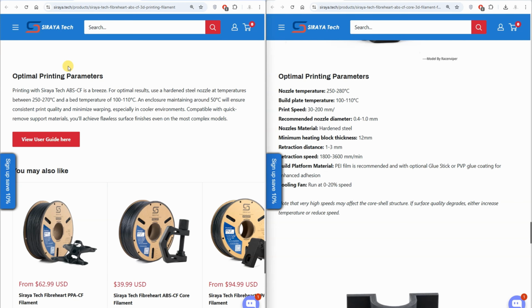And now the print settings. The print temperature in both cases is very similar. For the carbon fiber version, the nozzle temperature is between 250 and 270 degrees Celsius. On the core version, the maximum is 280 degrees Celsius. The bed temperature is the same, between 100 and 110 degrees Celsius. And of course, we have to use the hardened steel nozzle. The fan between 0 and 20%.